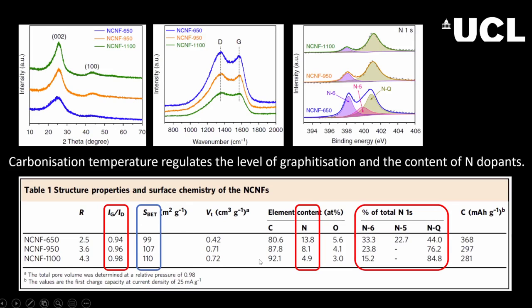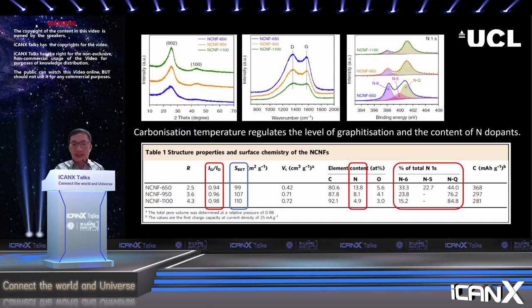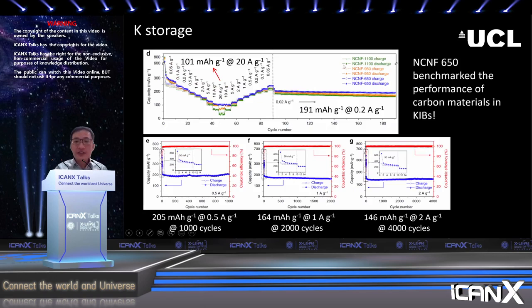What is very much different among the three samples is the content of the nitrogen doping and the type of each nitrogen doping in the material. I will come back to this later to explain how exactly nitrogen 6, nitrogen 5, and the nitrogen Q affect the battery performance. We started from testing the potassium ion batteries in the half cell configurations, and the results showed that the samples that is carbonized at 650 degrees showed the best performance, not only in a low current density,